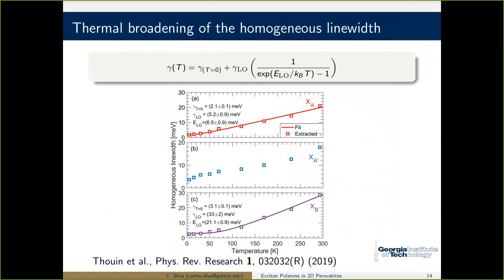Not only that, but if we do a temperature dependence, so we ask what is the main effective phonon that is responsible for exciton scattering that leads to the dephasing. We see that for exciton A, we have a phonon that is basically something in the spectral range that I showed you from that time domain Raman spectrum. In fact, this is pretty close to that M6, that's a slightly out of plane mode.